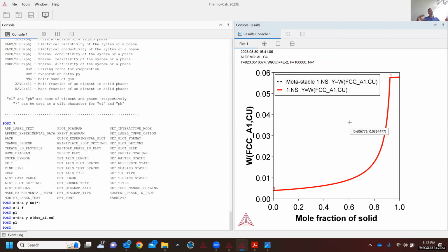And then if you're interested in a homogeneous alloy, this difference in composition will help you determine appropriate homogenization or solutionization heat treatment to eliminate that composition profile, because now we've got multiple dendrites that have 0.5% copper, and then we've got multiple interdendritic regions that have 5 to 5.5% copper. You look at your microstructure, you'll see it has a fairly regular spacing, which is called the lamellar spacing. And based on the lamellar spacing and the delta in composition, you can find out what the diffusivity of copper in aluminum is, solve the diffusion equation for a sinusoidal composition, and find out how long you need to heat treat it to get rid of all of this composition segregation. That's it for today.